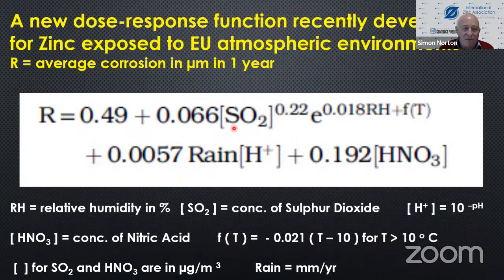There is a model that's been developed for European Union atmospheres, and I would imagine that it could be used in South Africa relatively easily. You need to measure how much SO2 is in the atmosphere. The relative humidity you can measure easily with an instrument. The temperature equation, you can just measure the temperature yourself. The pH you can measure by measuring the rain pH. And the nitric acid, well, there's very little in our atmosphere, but if you can measure it, you do. Otherwise, you just make that term 0. And there you get the average corrosion rate in microns in 1 year. It's quite useful.